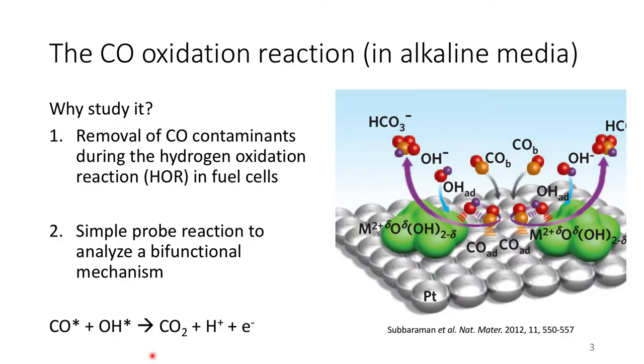So in this work, we're looking at the CO oxidation reaction in alkaline media. So why would we be interested in this reaction? Well, 2 reasons. First, this reaction is useful in hydrogen fuel cells to remove CO molecules that can hinder the hydrogen oxidation reaction, or the HOR, at the anode. Second, it's a simple probe reaction to analyze bifunctional reaction mechanisms since it only involves a single electron transfer, as demonstrated by the overall reaction.